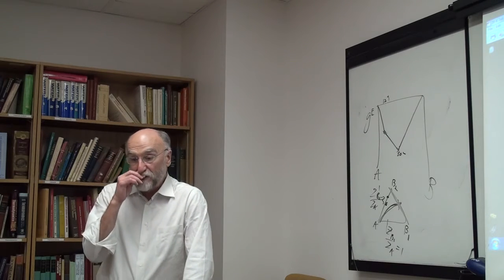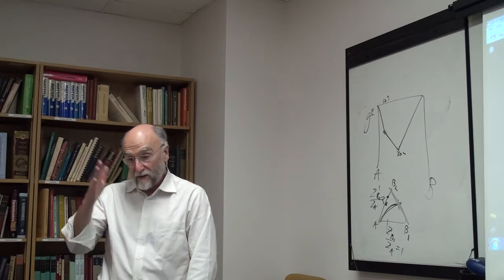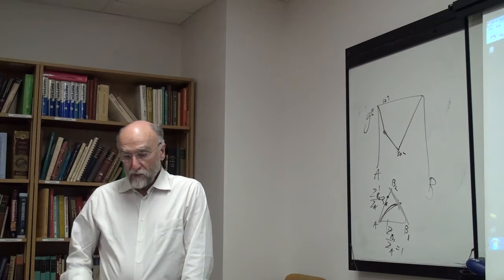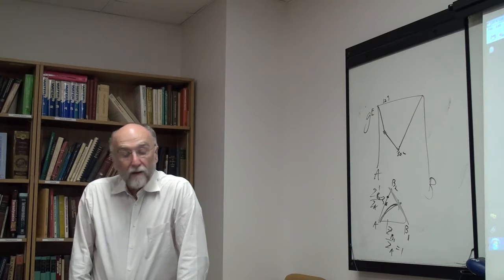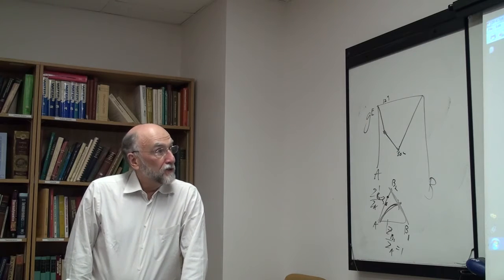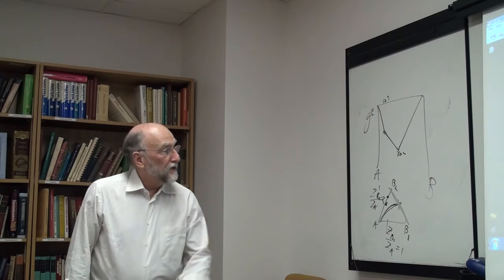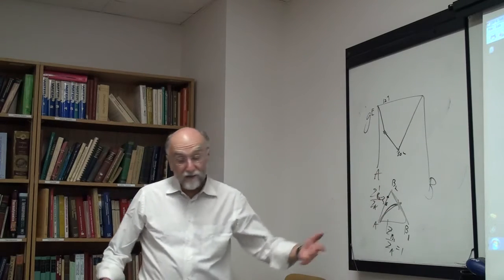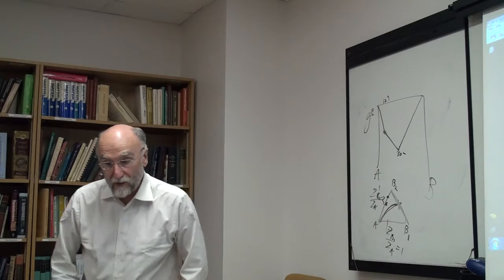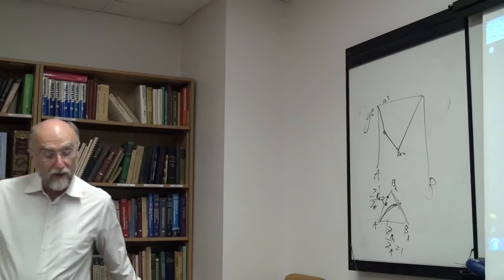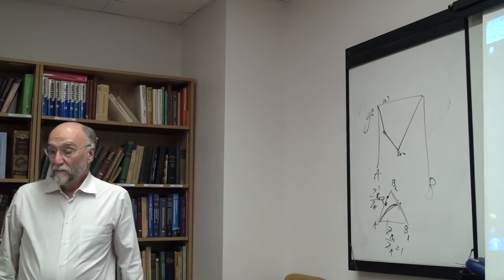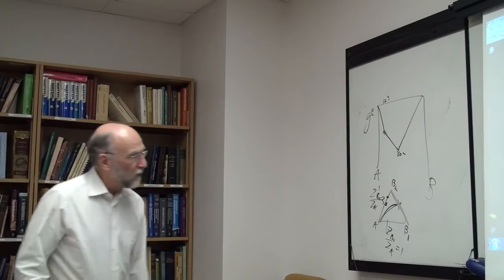In the cryolite system between NaF and AlF3 you have at least two compositions of maximum ordering, for ratio of 4, ratio of 5, not a ratio of 6, which you might expect. And these are treated by talking about different kinds of aluminum fluoride. I won't go into the detail, but there are ways of extending the quasi-chemical model to actually treat more than one minimum.